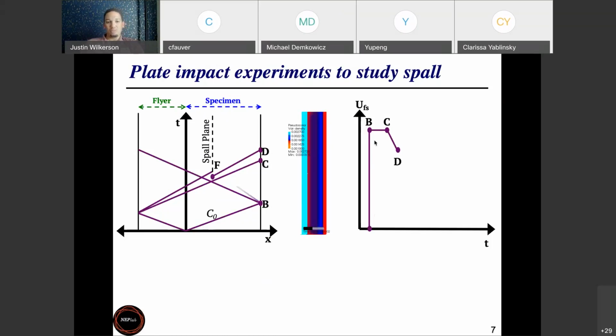Whereas when you release, it's the opposite. So when you release, you are taking material that's highly compressed, and that is what's first being released. So you're going from 10 GPa compression down to 9, and that's the fastest wave because it was at the most compression. So it runs away first, and then the packet that comes from 9 to 8 moves a little bit slower, and then 8 to 7 moves a little bit slower. And so all those packets are moving at slightly slower speeds, and so they spread out. That's why we call it a rarefaction fan, because as it releases off, it spreads out. And so that's why when we come with the release waves off of point B and off of this point over here, we spread out like that.